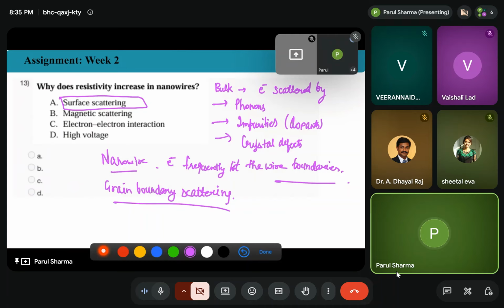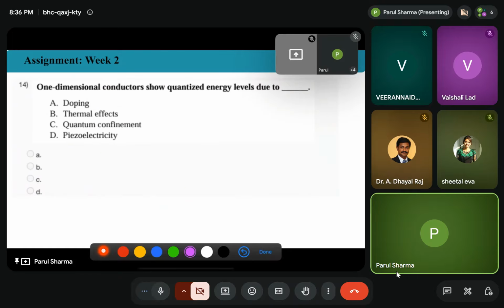Also because of surface defects: since nanowires have a very large surface to volume ratio, their surfaces can contain oxide layers, defects, surface roughness. That will create additional scattering centers for the electrons. So that's why the resistivity will increase in the case of nanowires. So what is the cause? Surface scattering. What is the effect? Increased electron collisions. Then grain boundary scattering reduces the electron mobility. Quantum confinement affects the electron transport. Oxidation or surface defects add more scattering centers. Because of all of these, the resistivity increases.